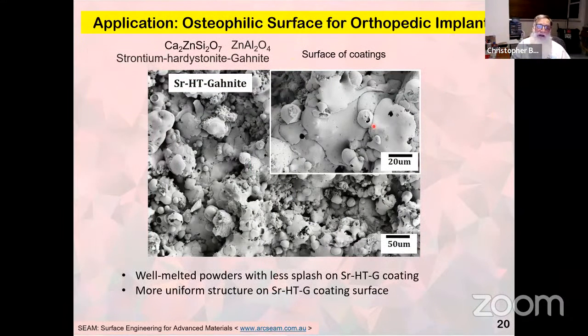So here's another example of a coating looking from the surface. And this is strontium zinc silicate, used for an orthopedic implant, not used yet. Now, this material is very interesting because it has antimicrobial properties. This coating, because of the zinc and the silicate, can kill bugs. So it's highly desirable. The hydroxyapatite, the gold standard, doesn't do that, whereas these new coatings do.